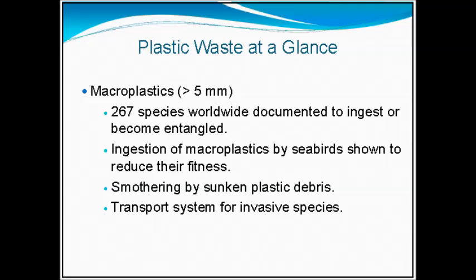So 267 species worldwide have been shown to ingest these materials. Ingestion of these plastics by seabirds tends to reduce their fitness. They usually end up dying from starvation because they become impacted by these plastic materials. Of course, things can be smothered by sunken plastic debris, or transported by invasive species associated with these materials as well. One of the things that's interesting is that in the last couple of years, people have actually started to look at these microplastics. What do they look like in terms of distribution and size?